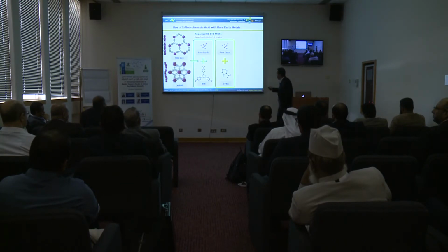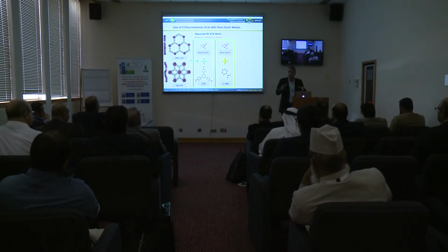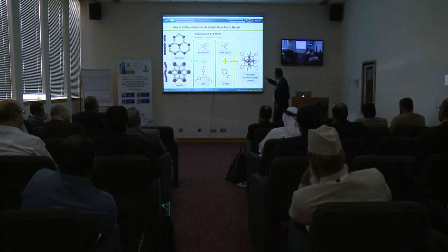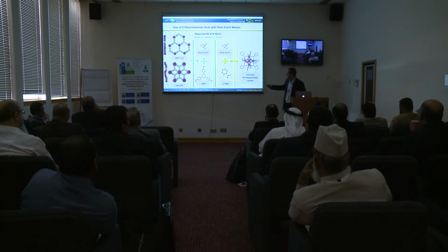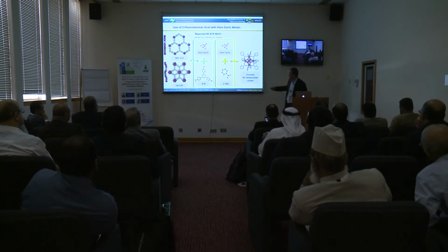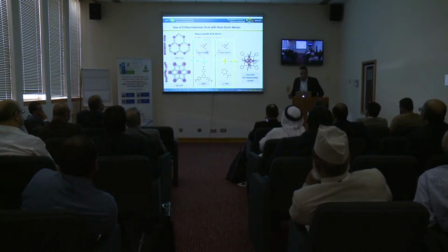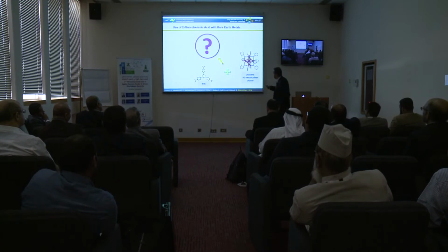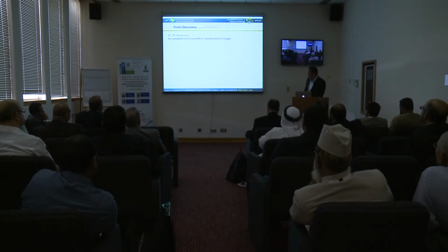So again, if I take rare earth, fluorobenzoic acid, I can make this hexanuclear cluster without a problem. And this was proven crystallographically. Take this DMF, I can make this cluster. However, if I take this and this and this, you get only this if you don't have fluorobenzoic acid. So that means that here I have room to discover structures that don't exist. So this and this are not compatible, meaning that I can discover new structures.